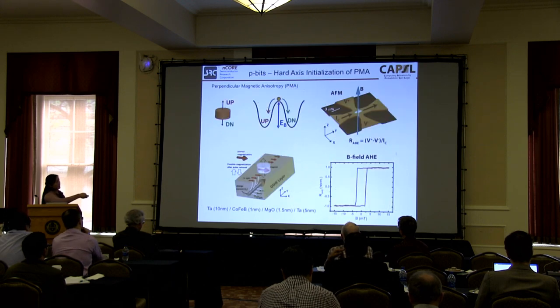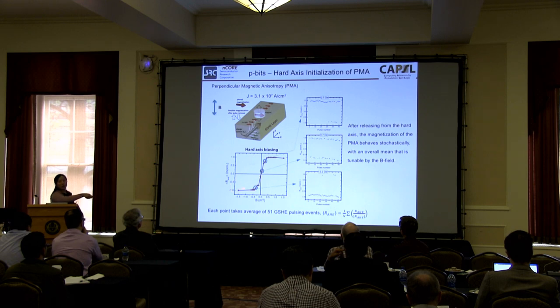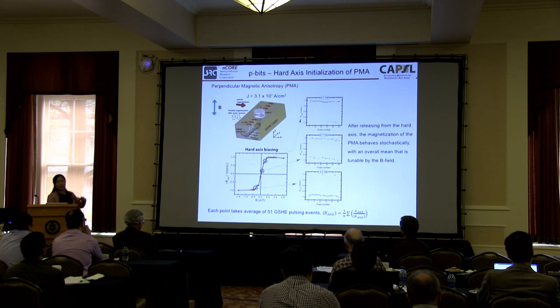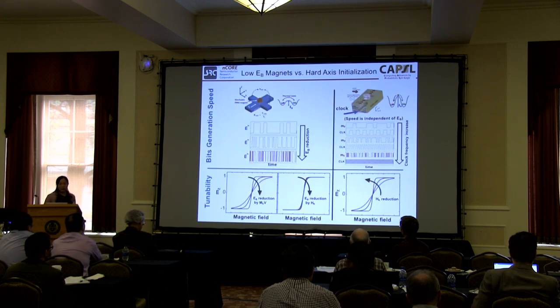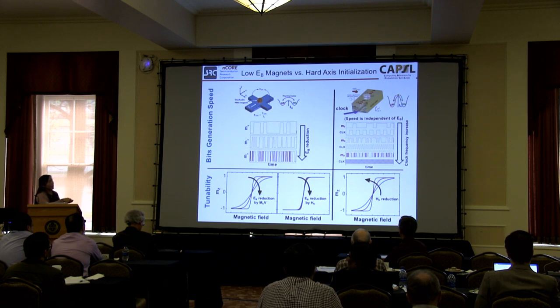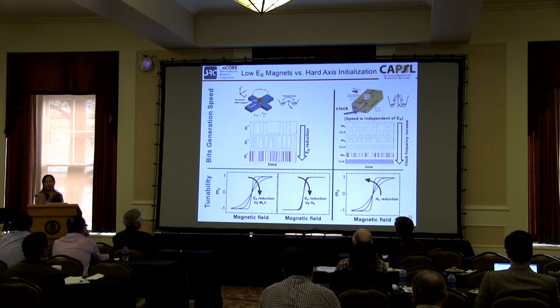And you can see, the original magnet is a normal magnet with a hysteresis curve. But once we apply this large SOT current, we can actually create the sigmoid curve. And again, without any input, because of the equal probability of going up and going down from the hard axis, we have an average of zero magnetization, while if I start to apply a magnetic field again, I can create the sigmoid curve. So this is the means by which we are trying to create stochastic magnets out of PMA nanomagnets.